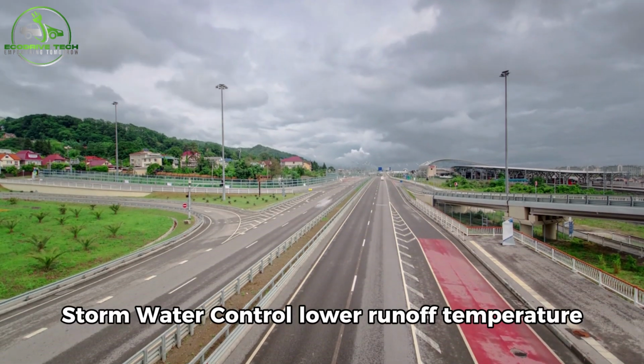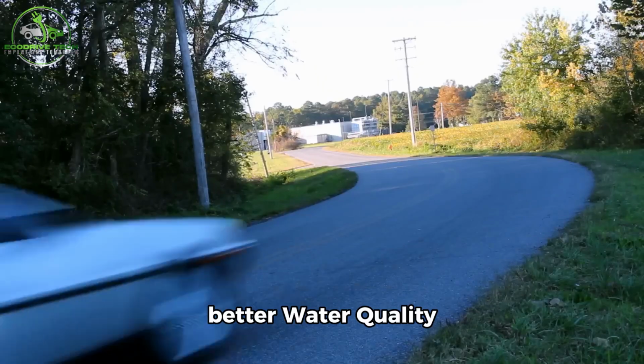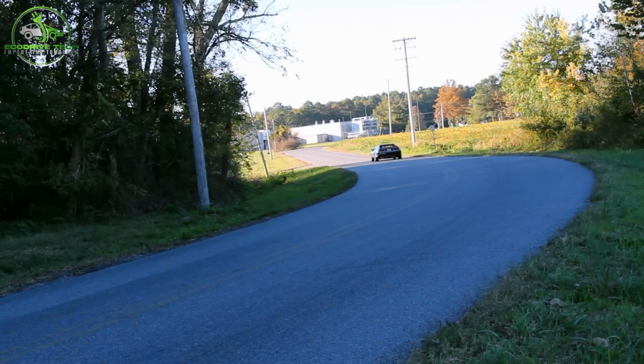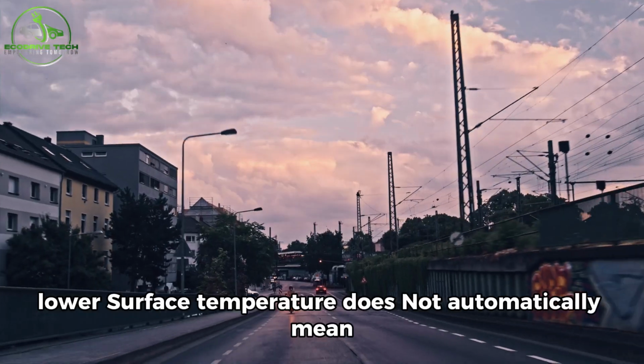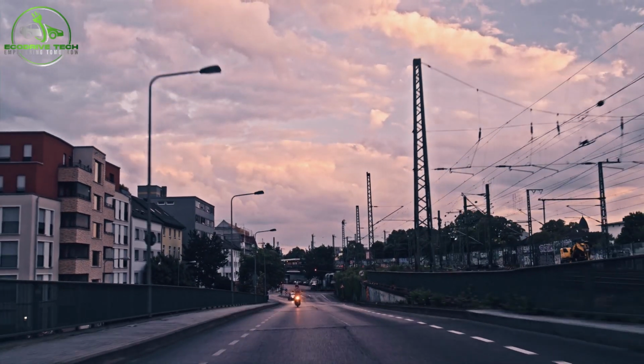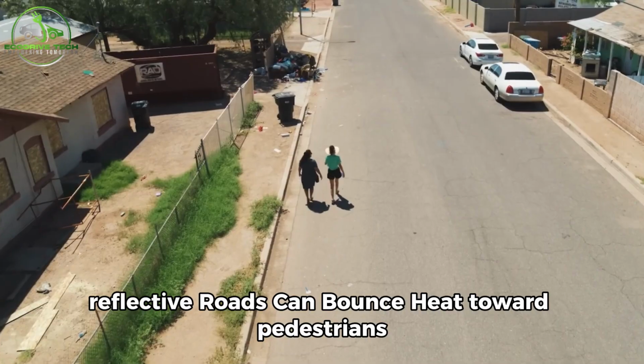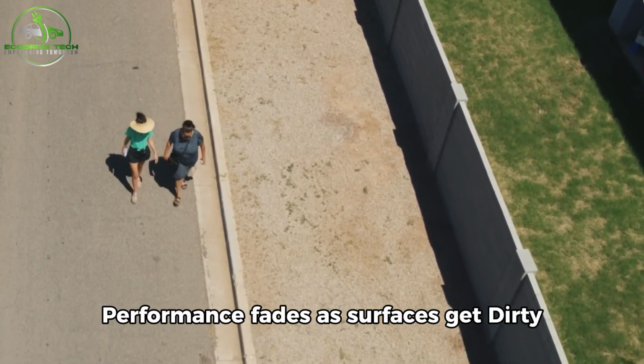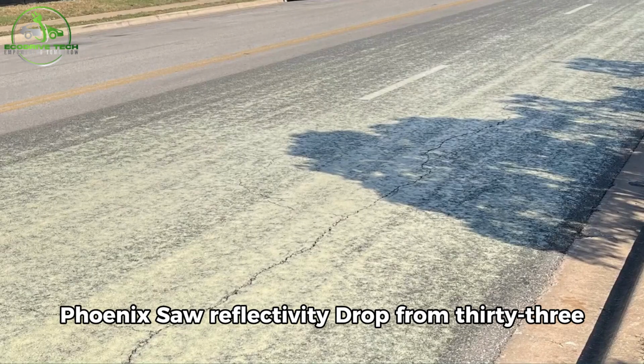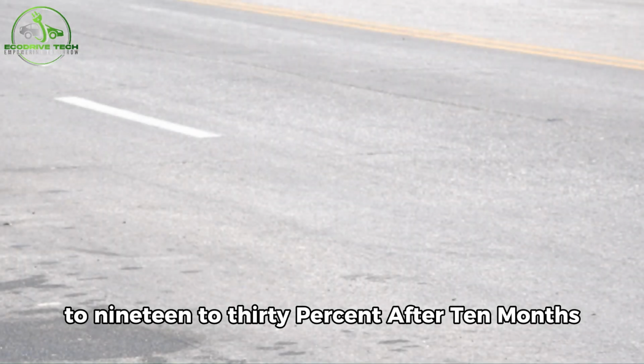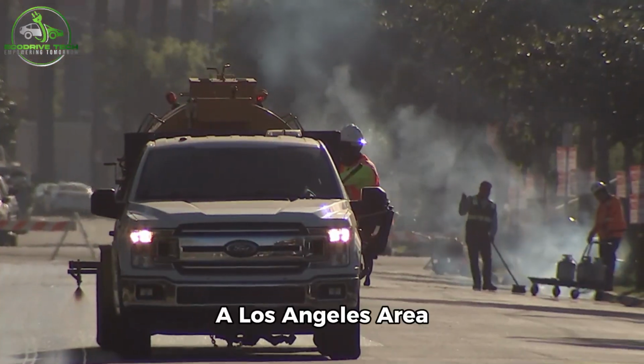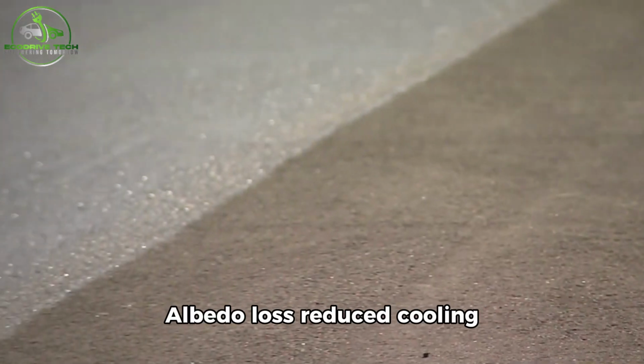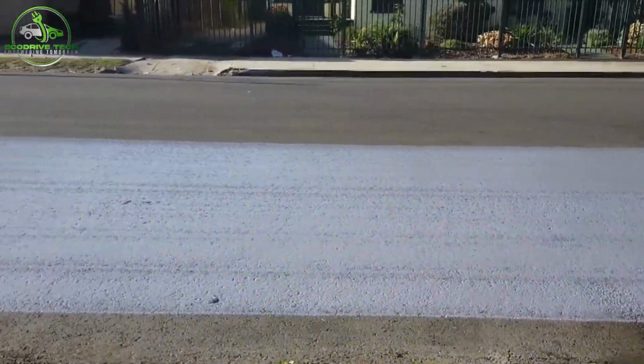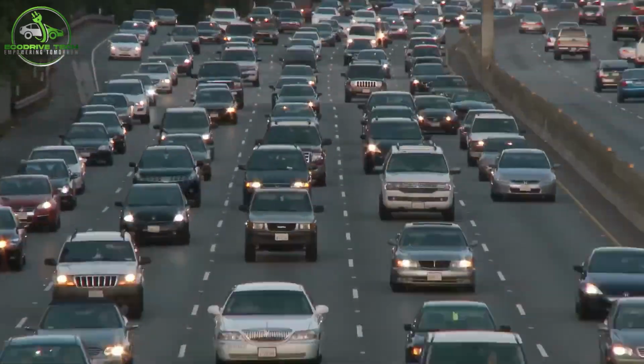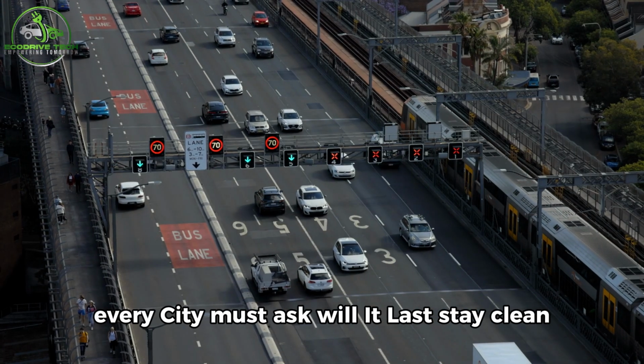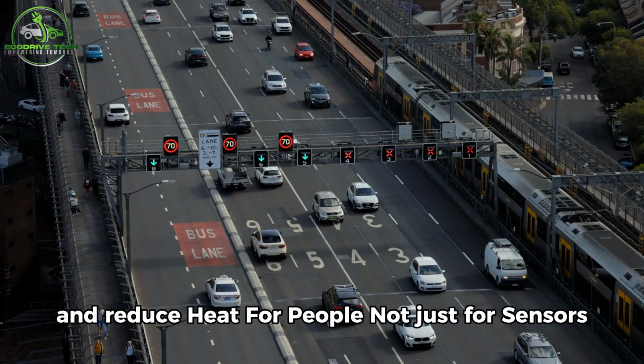Cooler surfaces, stormwater control, lower runoff temperature, better water quality, visibility, and heat health support. The criticism is serious. Lower surface temperature does not automatically mean better human comfort. Reflective roads can bounce heat toward pedestrians. Performance fades as surfaces get dirty. Phoenix saw reflectivity drop from 33 to 38% after installation to 19 to 30% after 10 months. A Los Angeles area study found that a 30% albedo loss reduced cooling by about 1 degree Celsius. Heavy traffic can destroy some coatings. Every city must ask, will it last, stay clean, stay safe, and reduce heat for people, not just for sensors?